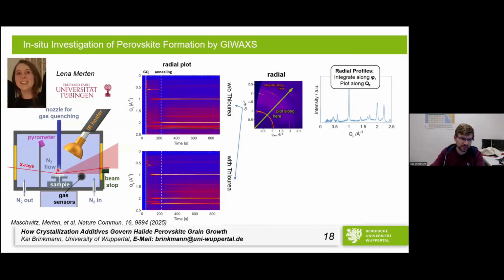Here you also see the setup. What we have is a gas quenching nozzle. So we didn't want to have the anti-solvent flying around there because it changes the atmosphere. We had an infrared heater, so we heated from the upside. And then we were basically having the X-rays hitting and looking at the parts at the same time. And the first thing that we did is we did the radial plot.